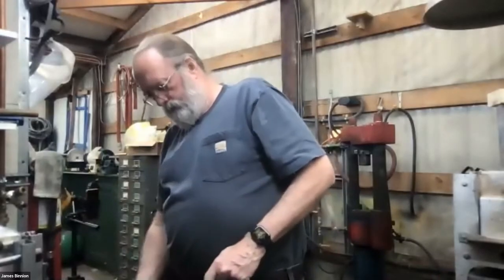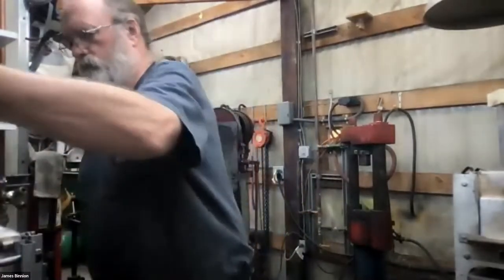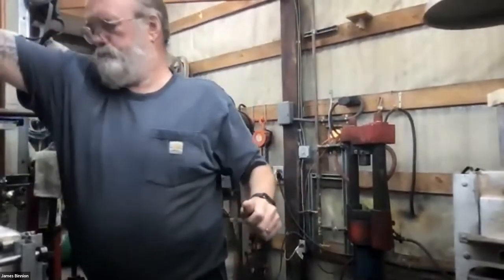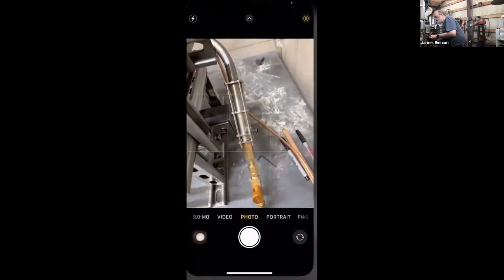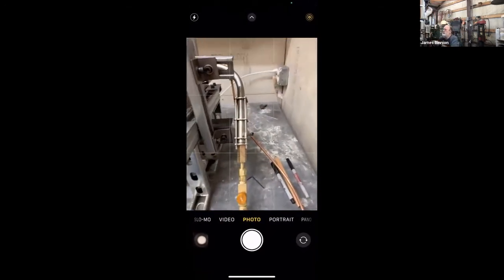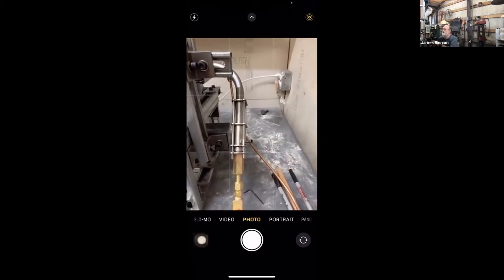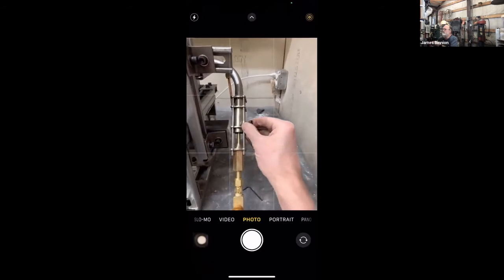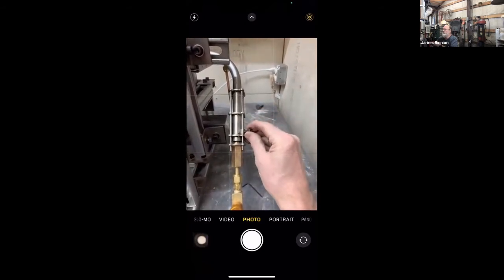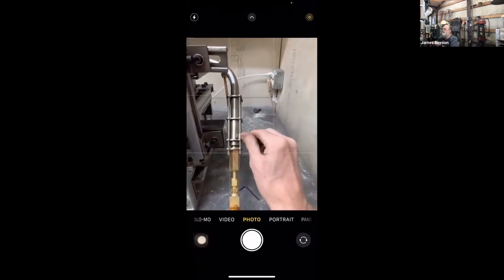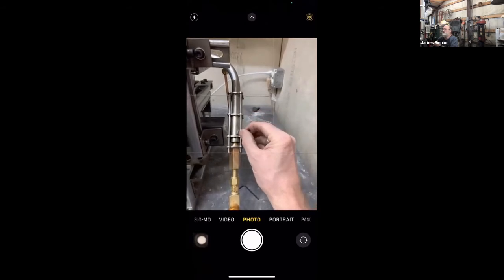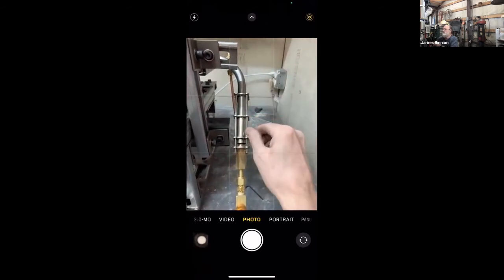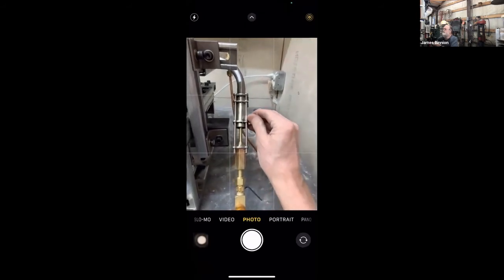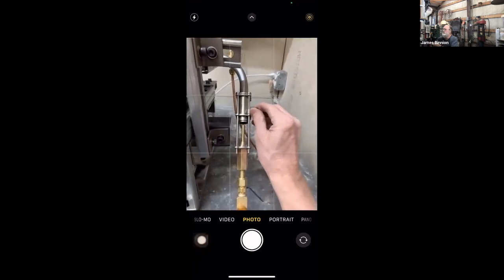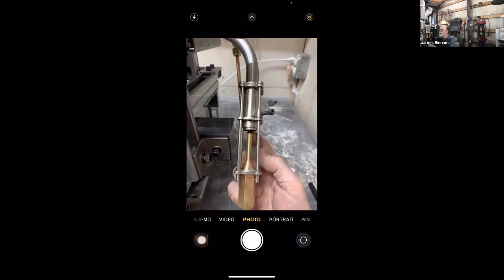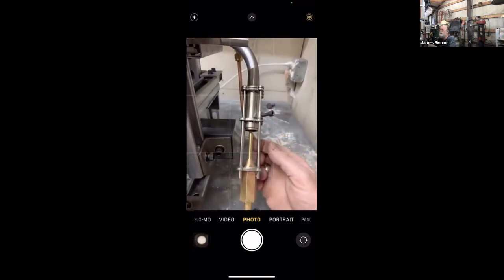Cool. Well, maybe while it's heating up, we can take a better look at your whole torch setup that's feeding. Yeah. So this torch is basically designed off of Mike Porter's torches that he put together, that really nice book on making propane torches. This is a piece of 3/4 inch diameter stainless tubing with a 7/8 piece of tubing sliding to give me the air valve. There's a little 16/1000 of an inch orifice in the end of this piece of brass.